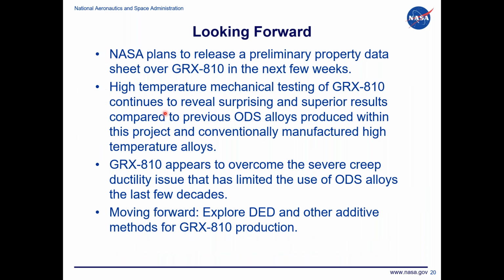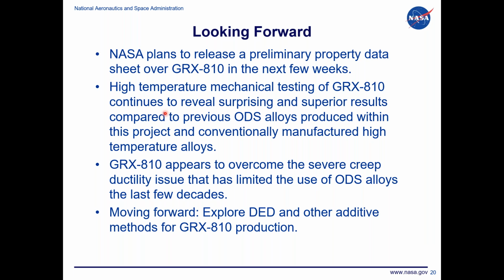Looking forward, NASA plans to release a preliminary property data sheet for GRX-810 in the next few weeks. We're continuing to do this high temperature testing of GRX-810, and we've also started testing other conventional alloys and their ODS versions. So far, GRX-810 has been far and above even those other conventional ODS alloys in creep at least. It appears to have overcome the severe creep ductility issue that you get with ODS alloys from the past few decades, and so I think that even further opens up the application space that you could potentially use this alloy.